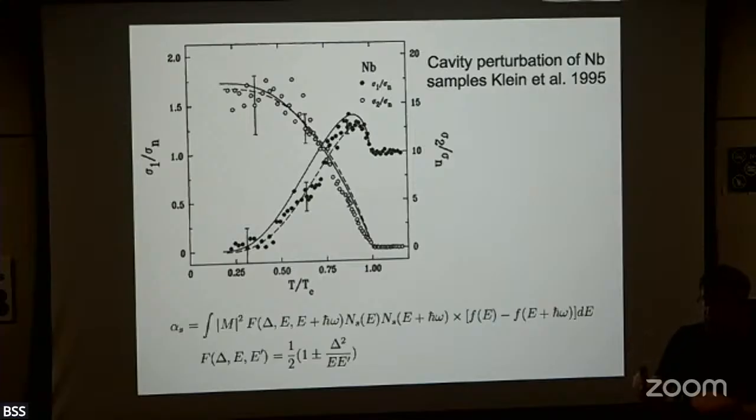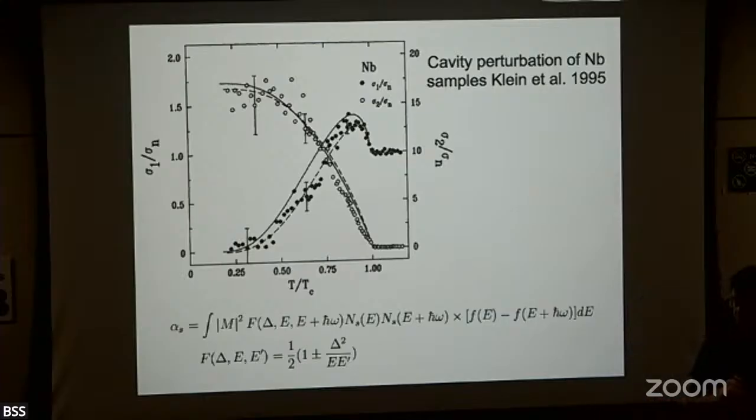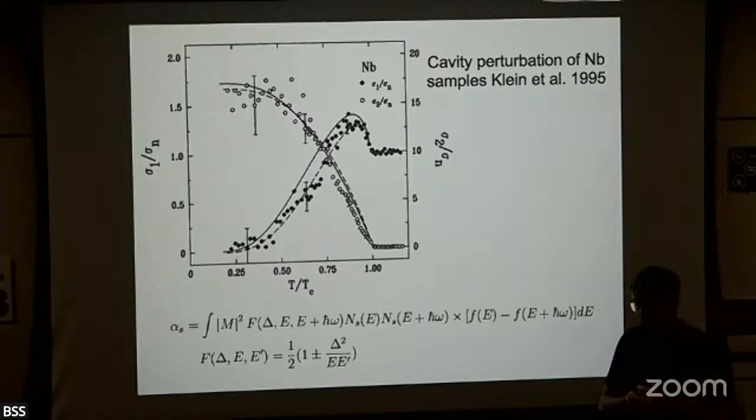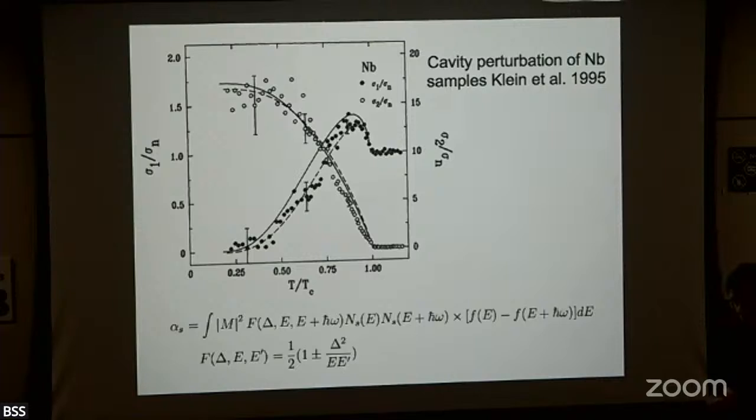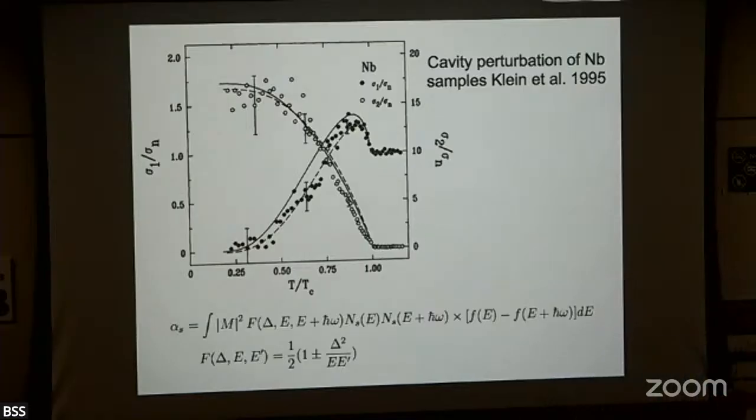So for instance, famous experiments were done on the temperature dependence of the superfluid density in D-wave superconductors. These were famously done by people at University of British Columbia. And so there, they didn't so much care about the overall magnitude of the superfluid density. They wanted to see how the superfluid density was degraded because you have nodes, presumably, in a D-wave superconductor as you warm up. So there, they cared about the temperature. They didn't even care about the magnitude of anything. They just wanted to know what was the power law. Or was it not a power law at all? Was it exponential? Was it S-wave? Was it what have you? And so there you don't even care about what the actual vertical scale is.